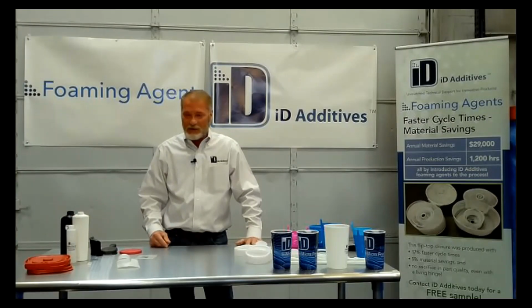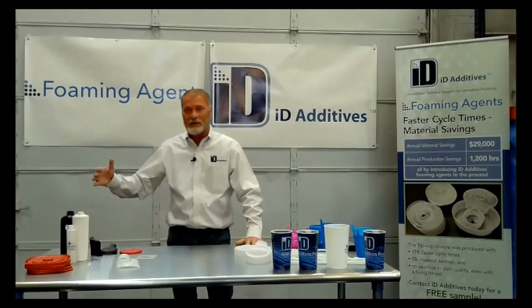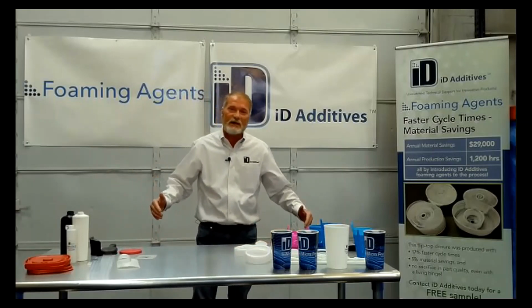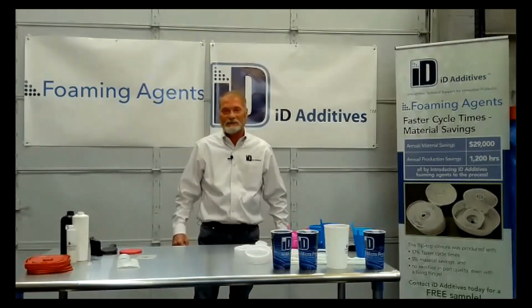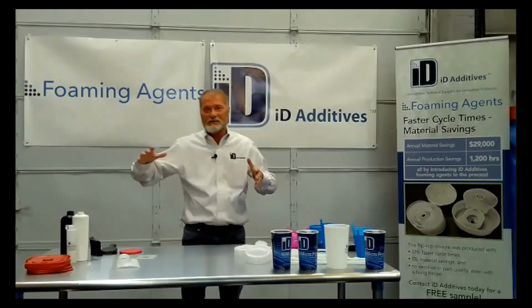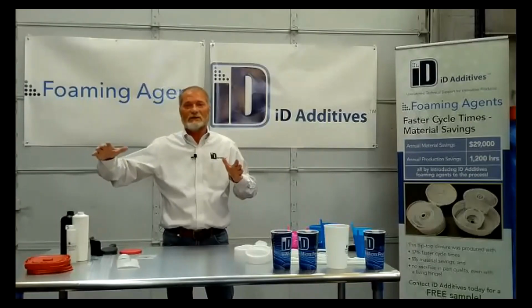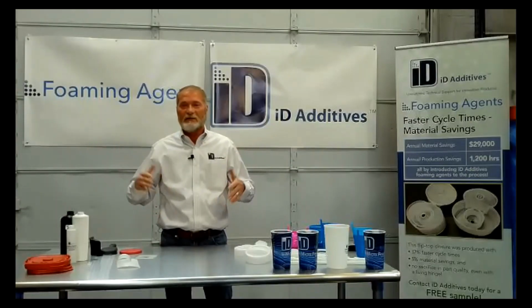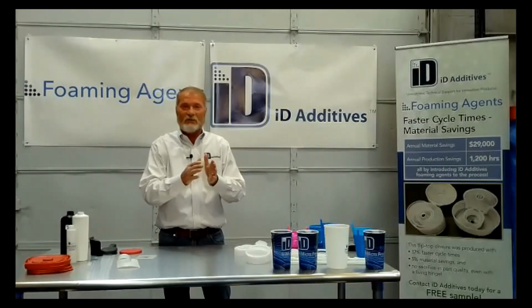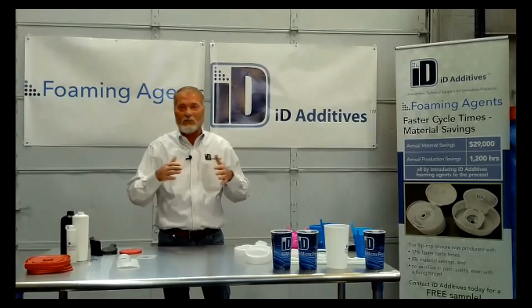Flow length is important as well. If you've got a big long flow length, that means you really need that velocity. Otherwise, by the time it gets all the way full, it's going to be pushing foam to the surface. The faster you inject it, the valley stays open, the foam migrates there. It doesn't want to go to the surface, but it can get pushed to the surface.